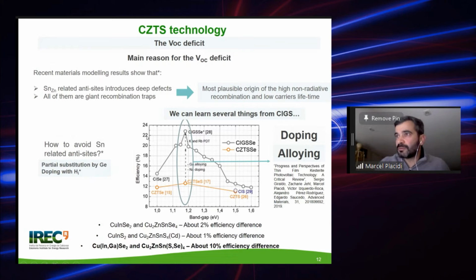So there are currently several strategies to avoid these tin-related anti-sites, and we are currently working on the partial substitution of tin by germanium, and also on doping with hydrogen. In fact, this was also advanced in the paper of Aaron Walsh. But there are so many things we can learn from CIGS, the cousin material.